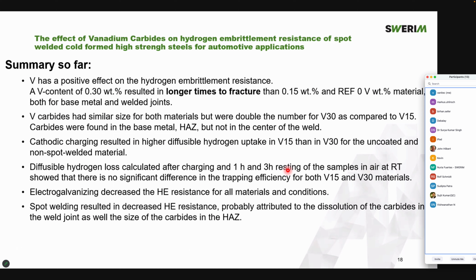We can also state that electrogalvanizing with zinc decreased the resistance to hydrogen embrittlement for all materials and conditions. And finally, we can say that spot welding decreased the hydrogen embrittlement resistance, and that's probably attributed to the dissolution of the carbides in the spot weld and the size of the carbides in the heat affected zone.